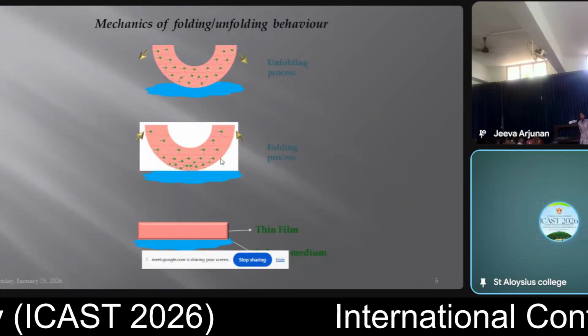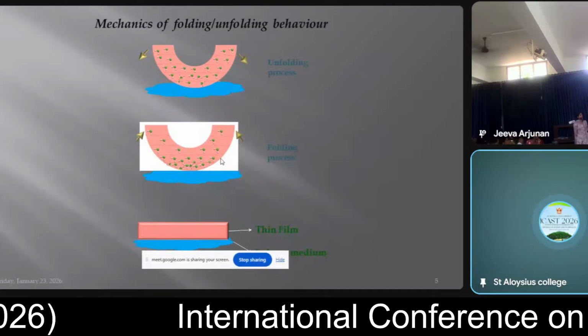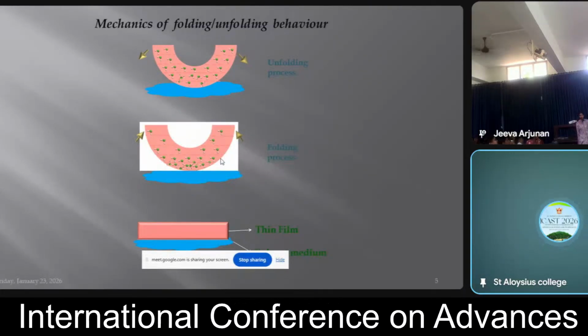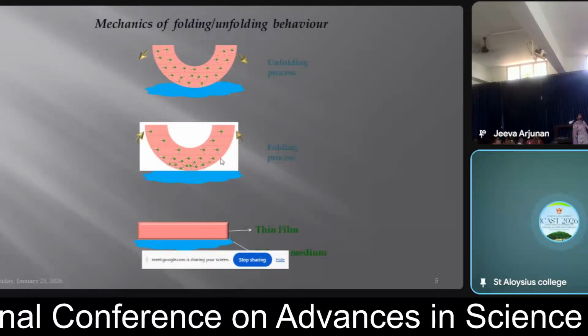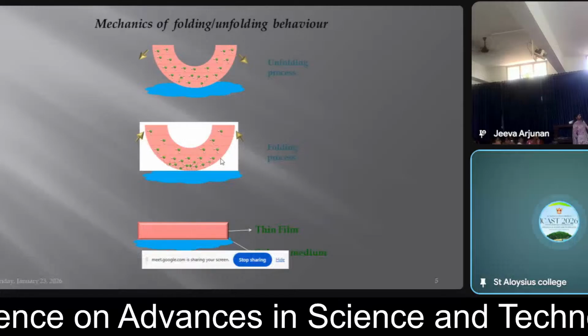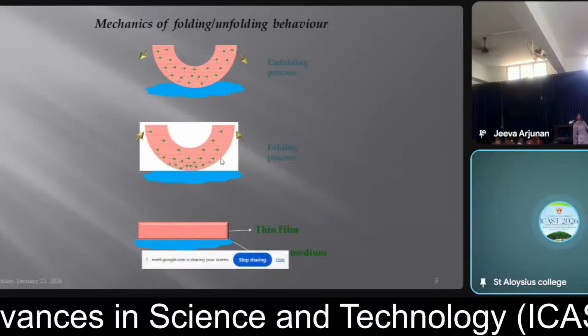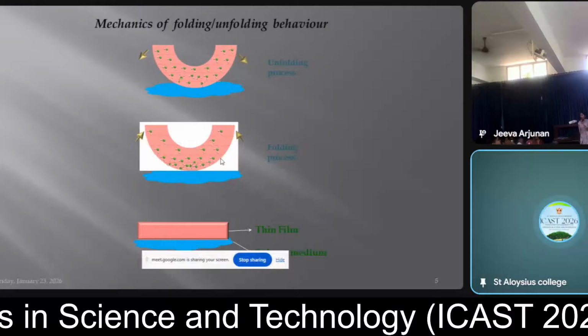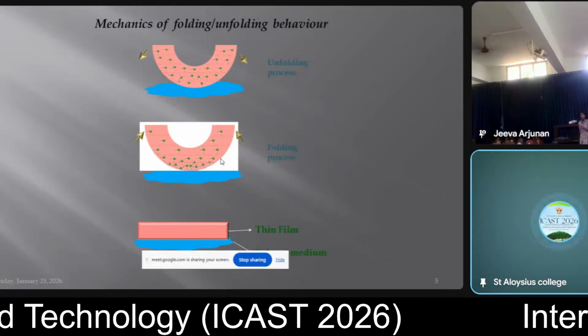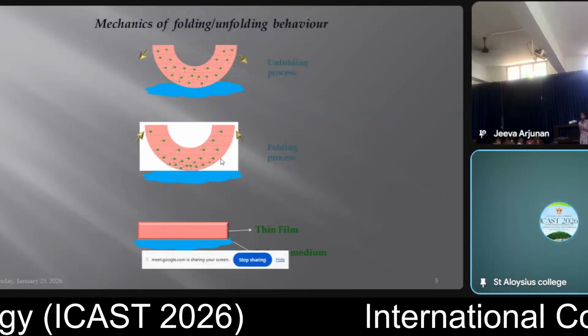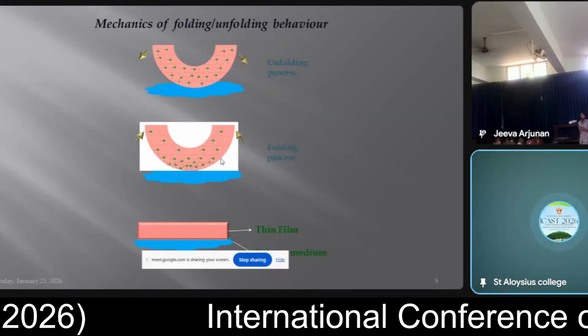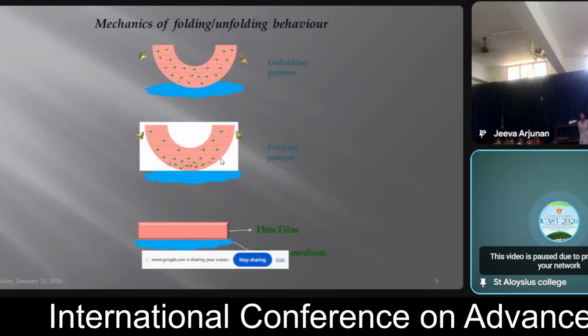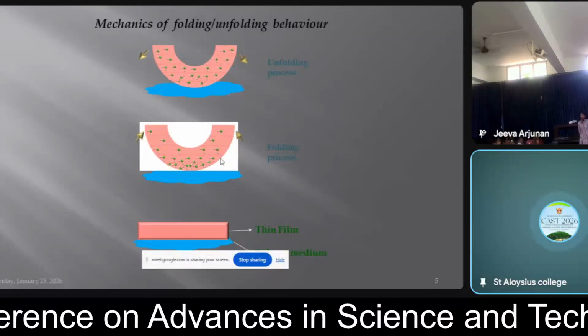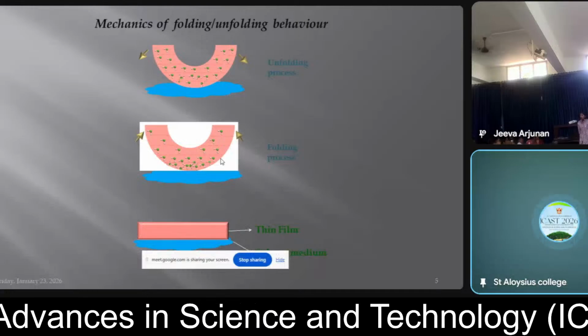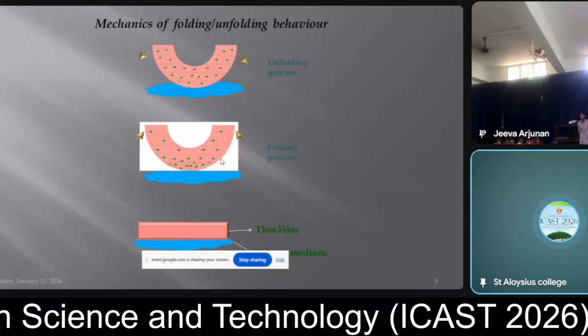So our title is self-folding behavior. What happens with chitosan itself? The rose-colored film is a thin film of chitosan. When it is placed above the water, it absorbs the water and starts to fold. When it has completely absorbed the water, it starts to defold. The mechanism is that, as I mentioned earlier, the chitosan film has amino and hydroxyl groups that interact via hydrogen bonds. When water comes, the hydroxyl groups form hydrogen bonds with the water, so it can easily diffuse through the chitosan film. That leads to the folding. Compression and stress form and then relax, and that's why it starts to defold.